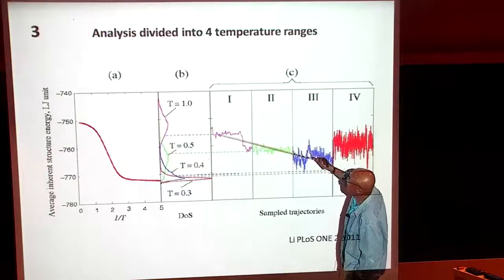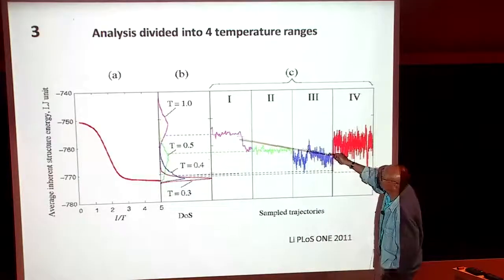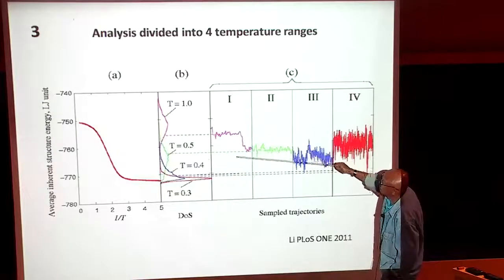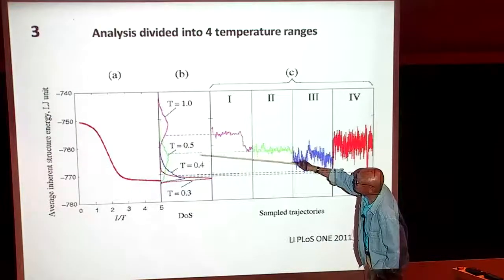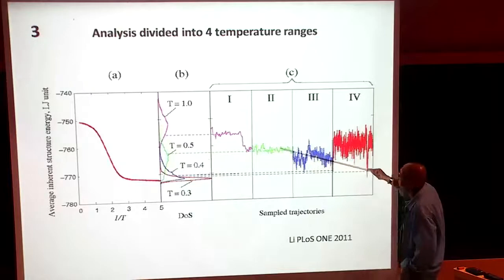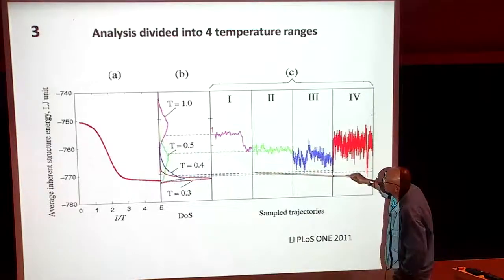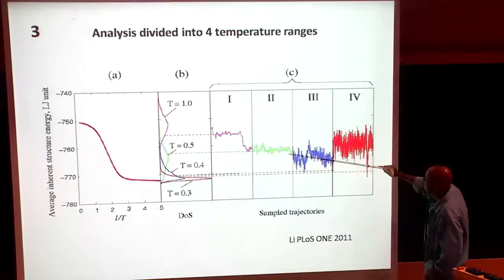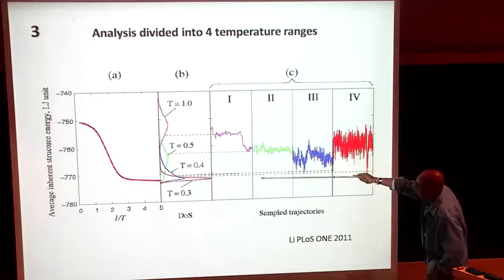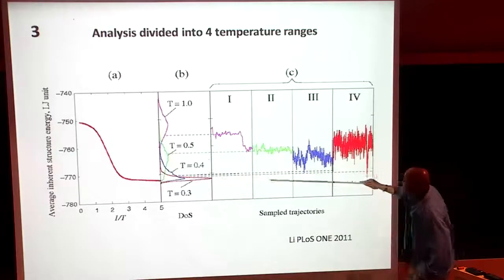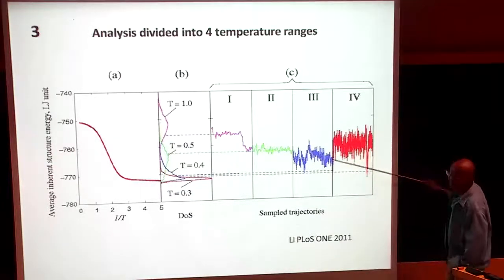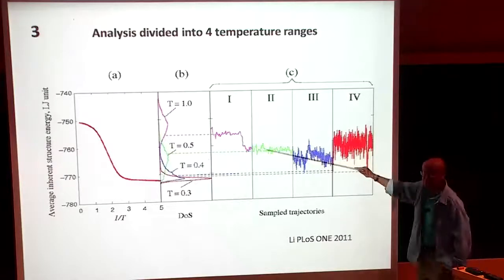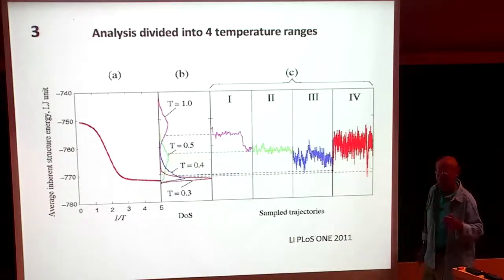We prepare a sample at T equal to 1, and we got the transition state pathway. That's what that one looks like. We prepare another sample at a lower temperature of 0.5, we got this green one, another one at 0.4, that's the blue one, and then finally the lowest one, 0.3, and that's this red one. And using this as input, we do Green-Kubo.